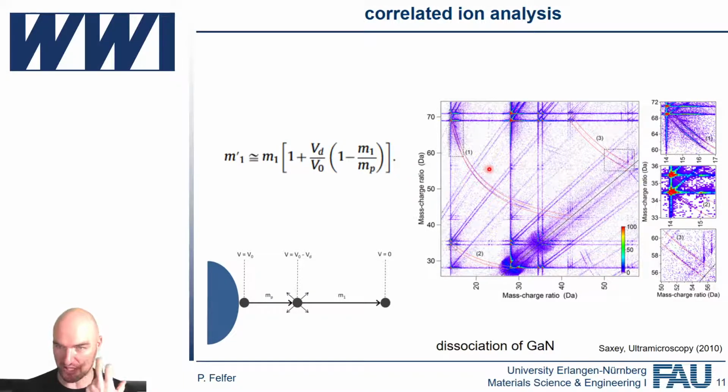But this is the mass to charge ratio that we measure, plotted, and you see that the parabolas that we get end in the individual ions that are making up the ion. So either they break up very close to here, then we just get the mass to charge ratios of the two ions that make that up. Or if they don't break up at all, it will end up in the combined ion. And we have a parabola, sorry, not a parabola, a hyperbola connecting the two ends.